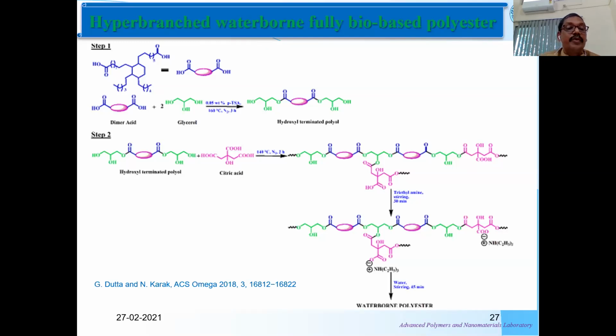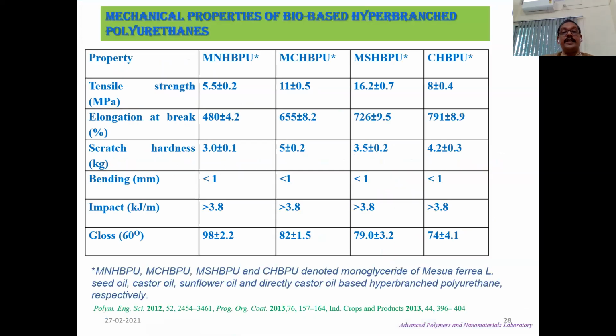In this process, we have successfully synthesized a fully bio-based waterborne polyester using dimer acid, glycerol, and citric acid, where we have not used any solvent, however a neutralizing agent, triethylamine, was used.